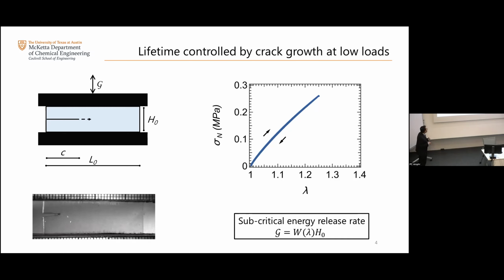And that's actually the question that I'm trying to understand in this talk, or one of the questions that I'm hoping to address over the next minutes. When you are in a subcritical point, below the critical point that it requires to go to fracture, you can still define an amount of energy that is going into your system, a G, energy release rate, but it's subcritical in nature. So what actually is the mechanism that drives that fracture in a subcritical condition? How is it different from the case of the critical condition? And how can we understand how to design materials to be resistant to fatigue, cyclic loading, as opposed to monotonic loading and toughness, okay?